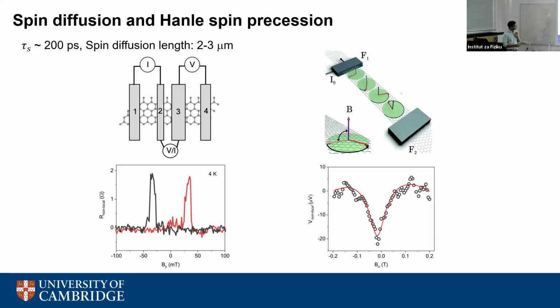Even with spin diffusion, you can measure this MR, which shows that this is not a charge-related phenomenon, but a purely spin-related phenomenon. And if you apply a field which is out of plane, what happens when these spins are propagating? The spins experience a Lorentz force, and they start precessing, and eventually they decay. With these measurements, you can calculate the spin diffusion times. This is the test to show that what we're observing is spin diffusion, not some spurious effects related to charges.